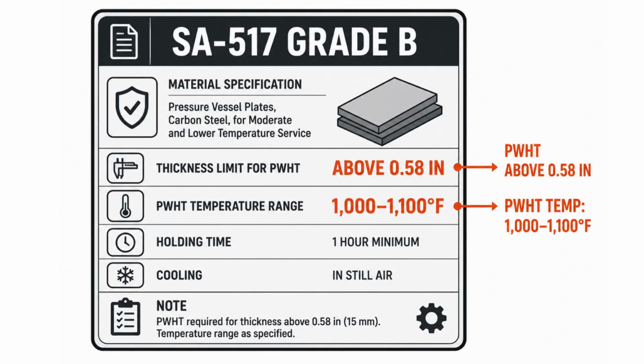Take SA-517 Grade B, a common UHT plate steel. PWHT becomes mandatory above about 0.58 inches thickness, in a tight 1000 to 1100 degree Fahrenheit window, a real number pulled straight from the material's own table, not a general Part UCS default. Miss that window in either direction, and you either haven't relieved the weld stress properly, or you've compromised the very strength you bought this steel for.